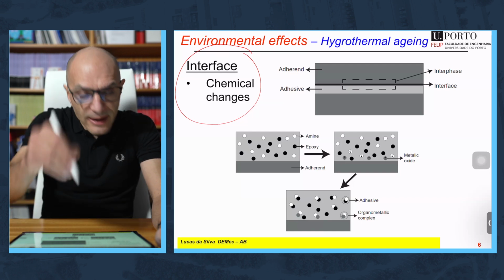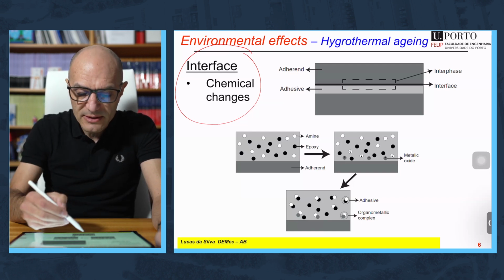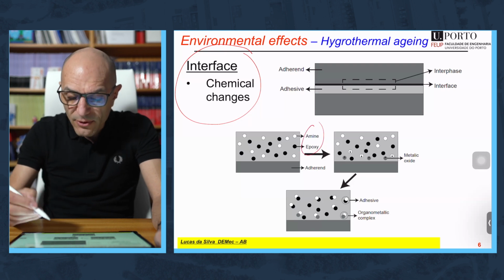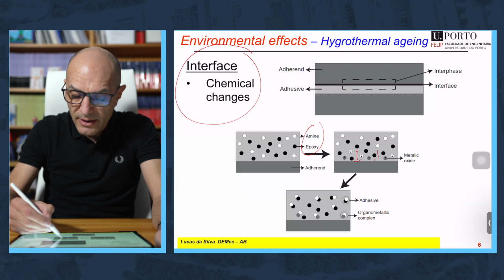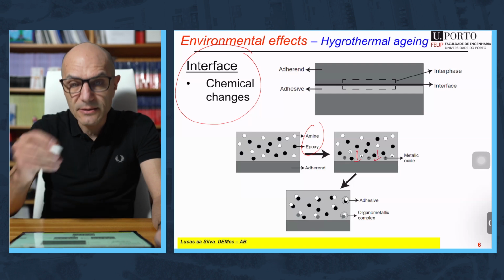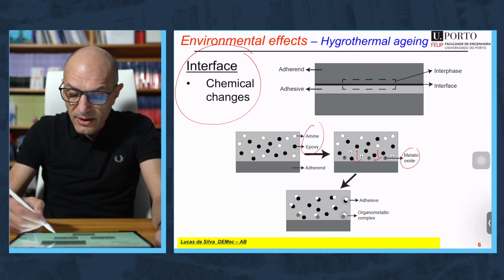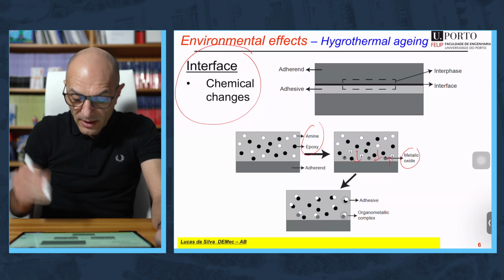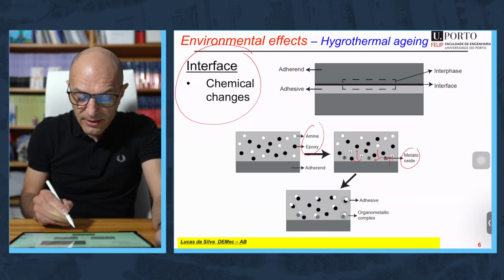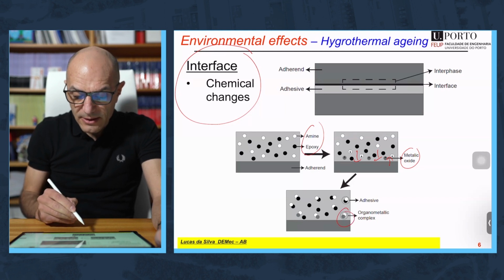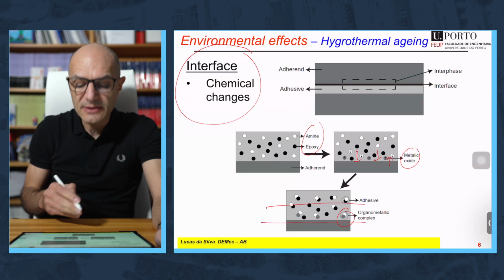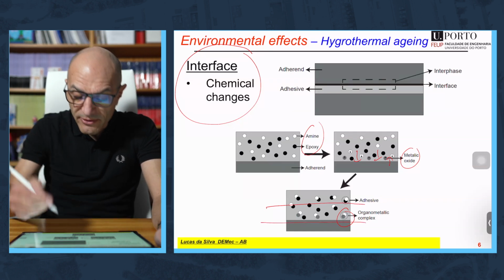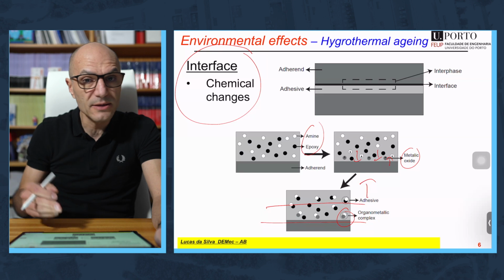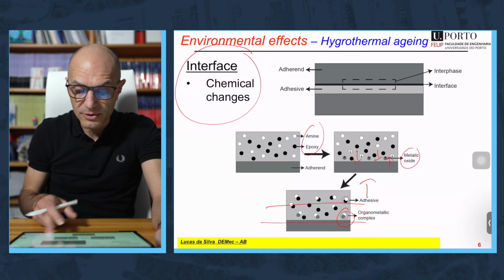If we look in detail at what happens at the interface, take for example the case where you have an epoxy that cures with an amine. First of all, the amine will tend to concentrate and go to the interface. Second, the metal oxide, when you use metals, will tend to be dissolved in the adhesive. And third, you might have a chemical reaction between the amine and the metal oxide. So really, here, close to the interface, we are talking about a different chemistry from the rest of the material. You have to take that into account if you want to have a proper joint design.